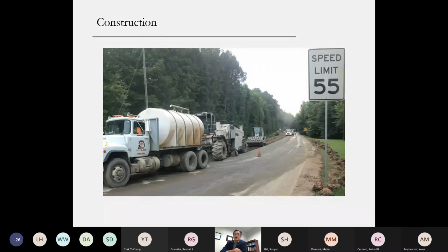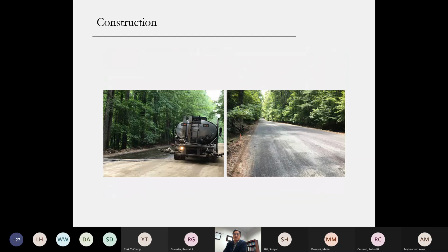After that, the entire pavement section was stabilized, and the reclaimer is pushing the water truck. Behind the reclaimer, a series of rollers follows: the sheepsfoot rollers and the smooth drums, and then the pneumatic tire rollers. After that, the primer is sprayed on top to finish the FDR base. The purpose of this primer is to prevent moisture loss during the curing of the FDR base.